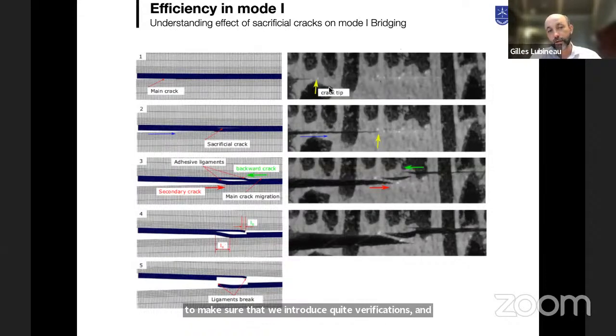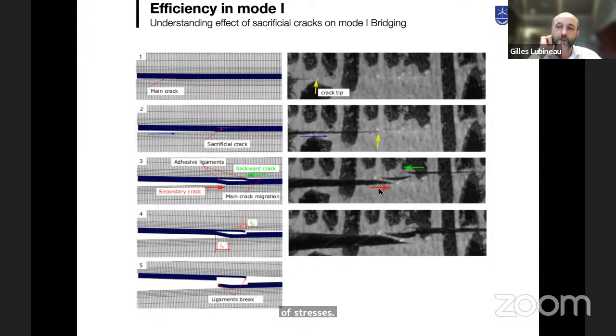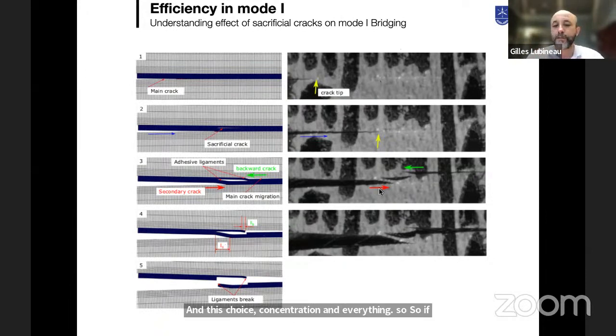So you see here, typically, instead of having a single crack delamination, due to the sacrificial crack that is here, we are going to introduce a bifurcation in the ligament. So it does not modify the adhesion per se, but what it does is that it modifies the redistribution of stresses and the stress concentration and everything. So it will promote different mechanisms, and here typically it promotes bridging and dissipation.